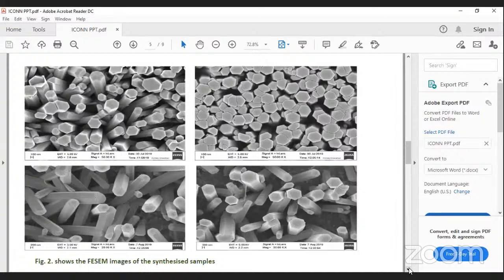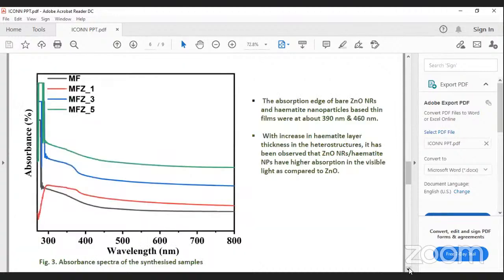The unmodified ZnO nanorods and MgFe2O4 nanoparticles modified ZnO nanorods have been analyzed by FESEM to investigate the surface morphology. The grown ZnO nanorods are vertically oriented, well-aligned hexagonal structures of almost uniform size with smooth surface. Now, the optical properties of semiconductors have an important role in the photoelectrochemical solar cell.